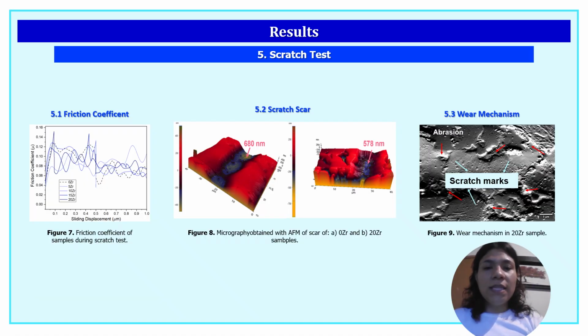The scratch test results provided the friction coefficients of each tribological pair. As shown in figure 7, at the beginning of the contact between the conical indenter and the sample surface, the friction coefficient of all samples is high. However, as the sliding distance increases, the coefficient decreases due to the reduction in roughness between the surfaces.